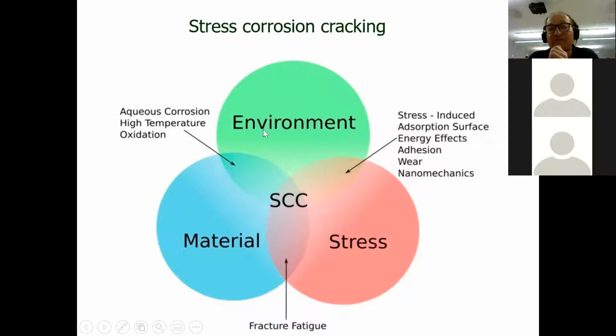And the third bubble is the environment itself. What are you exposing the material to? It could be seawater, for example. It could be high temperature, for example. It could be a corrosive gas like chlorine gas, for example. Remember, with stainless steel in particular, chlorine and chloride are very aggressive. So you can be certain that if the environment contains chlorine or chloride ions, and you have the stainless steel or high tensile steel under stress, you're almost certainly going to have the conditions where you'll get stress corrosion cracking occurring. So you have to be very, very careful when you design such components that you avoid the problem, or at least you know about it beforehand and do something about it.